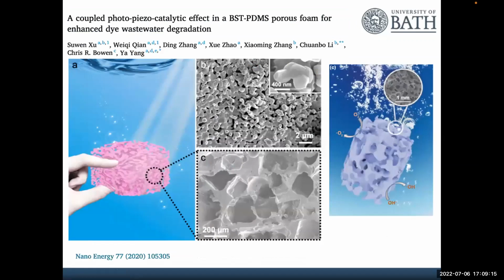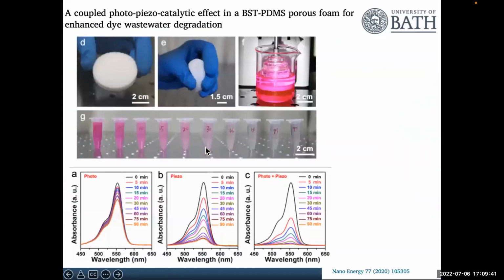And work that I've been doing with Professor Ya Yang, he's been using composite materials where you take the ferroelectric material and embed that into a porous polymer foam. And the pores in this case is really just to let the solution electrolyte enter the structure. And it's in a polymer foam because you can then mechanically deform the material to develop those charges. And that was used by mechanical deformation to achieve wastewater degradation of dyes, rhodamine B, for example, within the material.